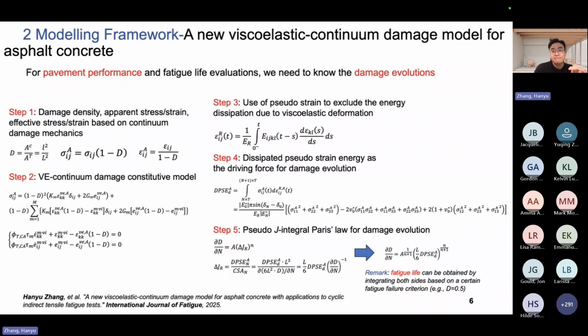Now we have the pavement aging model, and we also have a method to couple aging with mechanical analysis, but it's still not enough because we want to know the pavement damaging behaviors under the coupling effects of aging and vehicle loads. So I developed this viscoelastic continuum damage model for asphalt concrete based on Professor Schapery's theory. By using this damage model, we can know the indications of pavement remaining fatigue life based on the current pavement aging conditions and the stress state.